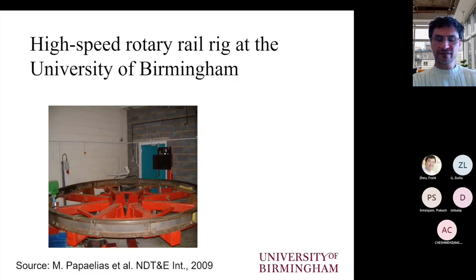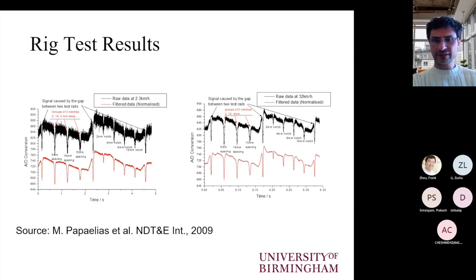Then we went on to test this on a high-speed rotary rail rig with a set of rails that had been prepared with a set of spark-eroded slots, and we repeated the tests up to 50 kilometers an hour. So you can see here the sets of tests for two different speeds, 2.3 and 32 kilometers an hour.